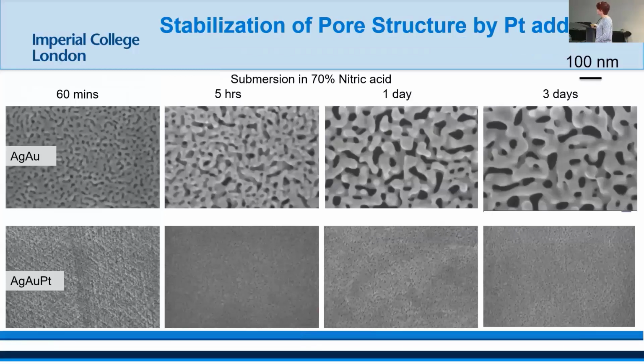I'm not going to talk too long about this. This is some work that's mostly being done by Jonah Erlebacher at Johns Hopkins. And this is one of Jonah's materials that he sent us. That gold coarsening is very rapid. And if you wanted to use gold in that way, you'd probably want to stabilize it. And what they realized is that, of course, it's all driven by surface diffusion. And platinum has got really rubbish surface diffusion, right? It's very slow. And actually, if you put a little bit of platinum into this alloy, and this is about 5%, it pins the structure, right? So you can leave it for a long time and it doesn't coarsen.